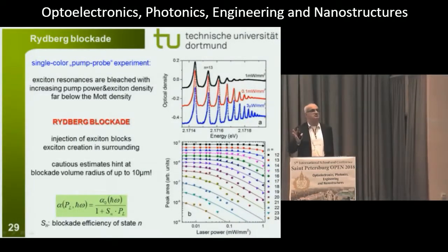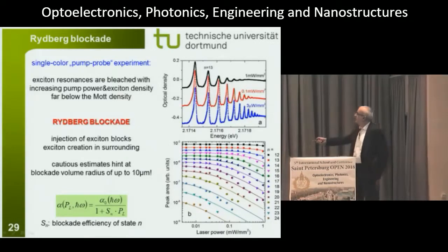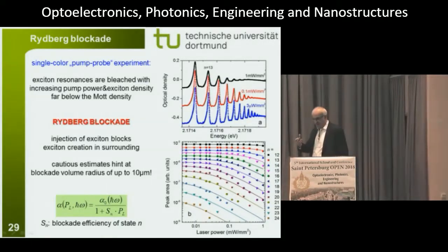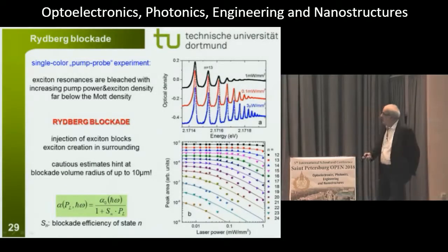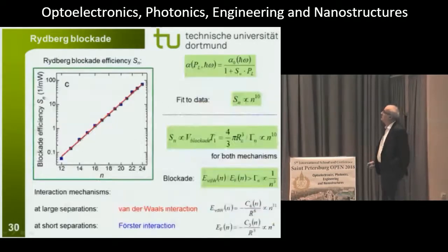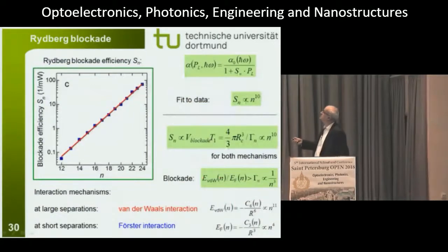This is obviously not possible, but let's say very, very low laser power so that we have no Rydberg blockade effects. So this is the ideal absorption without interaction effects divided by unity plus the laser power times Sn. And Sn is a phenomenological quantity which tells you how strongly such an exciton blocks the absorption. And when you determine these Sn quantities from the fits, you find this dependence on the principal quantum number.